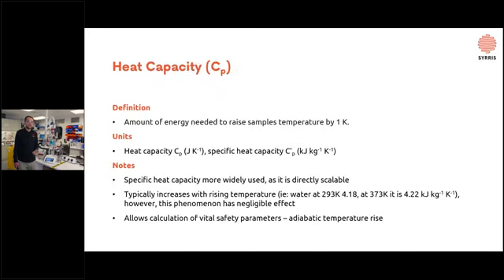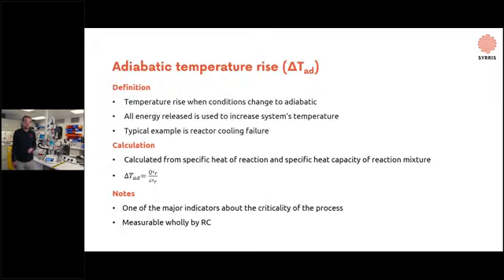Another important thing is heat capacity, the amount of energy needed to raise the reaction mixture temperature by 1 Kelvin. This is quite easily measurable during the initial screening test by DSC, but reaction calorimeters give us the possibility to measure it continuously. The specific heat capacity, again in kilojoules per kilogram per Kelvin, is very widely used because it's directly scalable. And it allows us to calculate vital safety parameters, one of the most vital being the adiabatic temperature rise, which we talk about now.